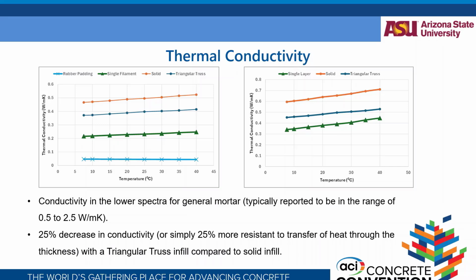So we had to calculate the equivalent resistance of the section and then the conductivity of the section. What we observed is that for the same thickness of wall, when we were doing a solid infill versus a V-shaped truss infill, we got a reduction in the conductivity. That's around 25% at the lowest, and it is a significant decrease.